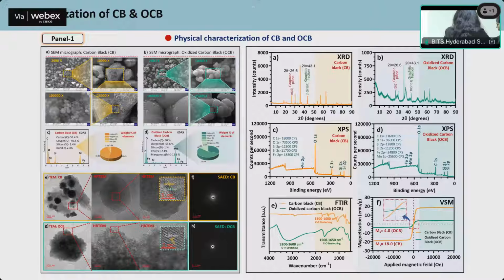TEM analysis also showed a diffused particulate morphology and a granular morphology in CB and OCB, corroborating with the SAED pattern with 0.24 nanometers of d-spacing. XRD analysis further confirmed that the material is amorphous and partially crystalline. XPS elemental analysis showed an increase in the percentage of oxygen, and FTIR gave us a glimpse of the introduction of OH stretching and CO stretching vibrations. VSM shows that the material is showing paramagnetic behavior.